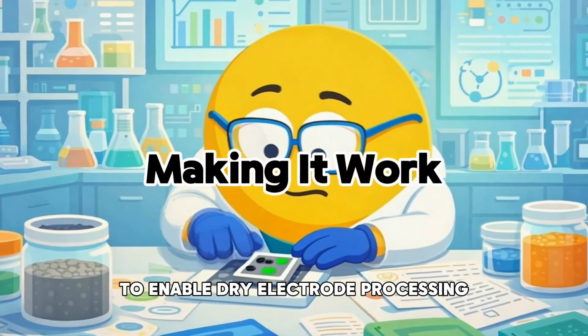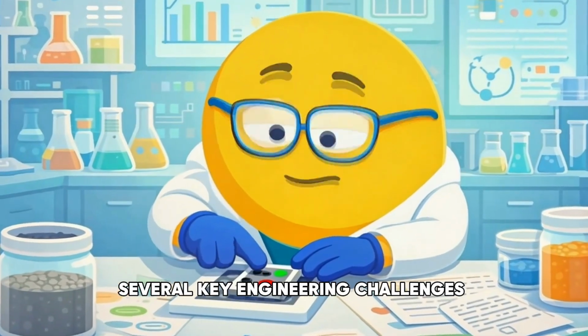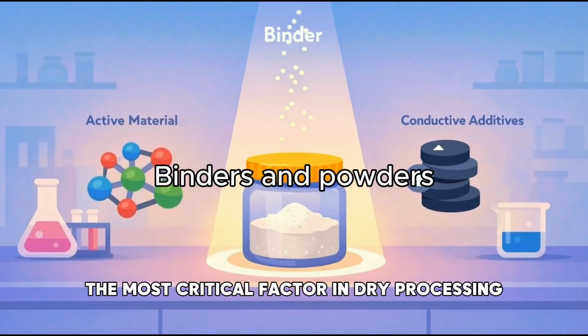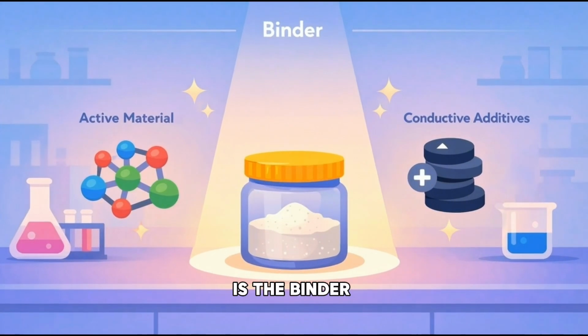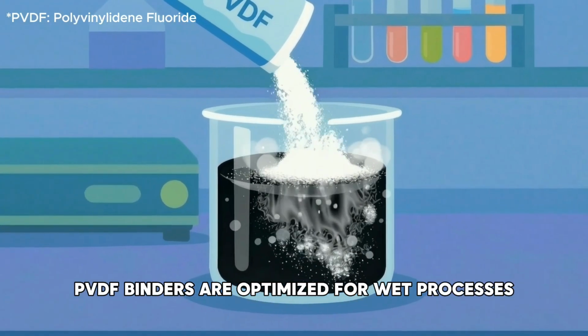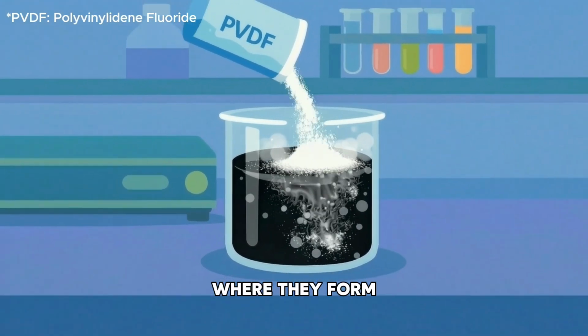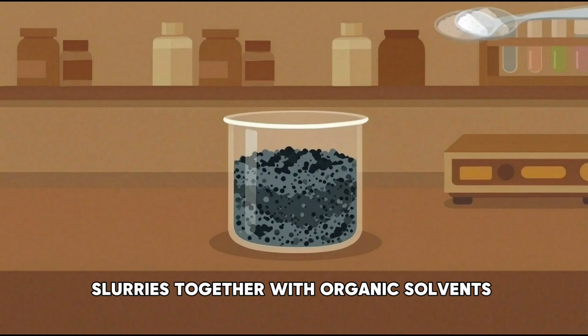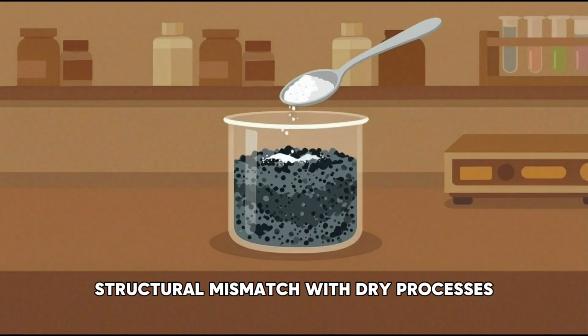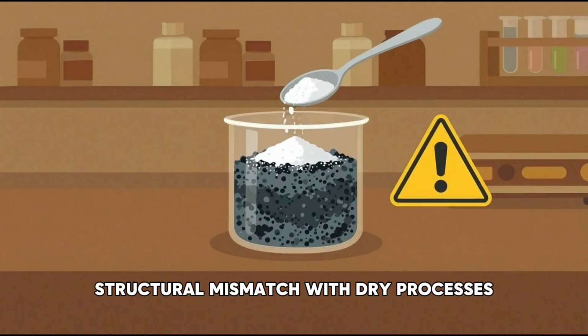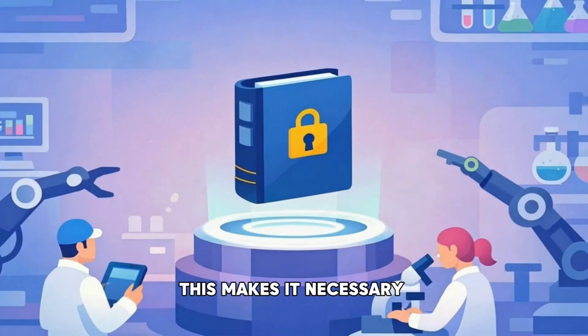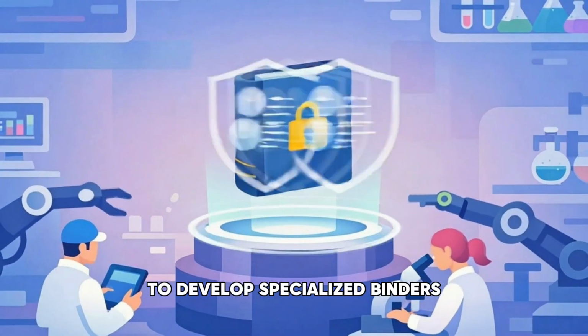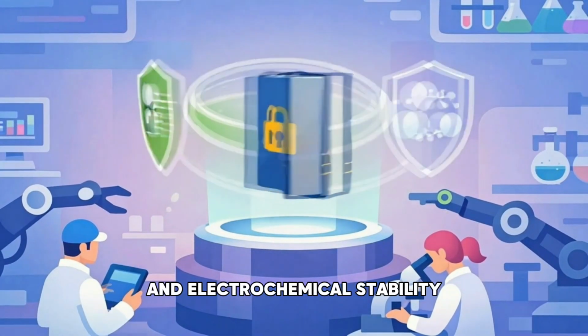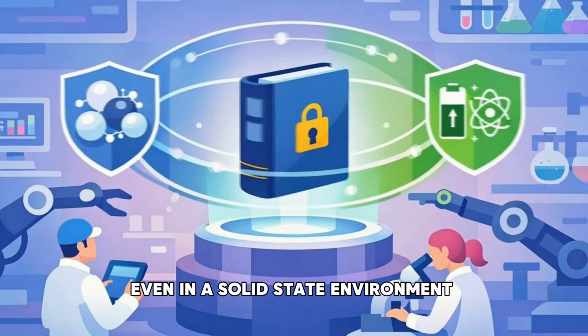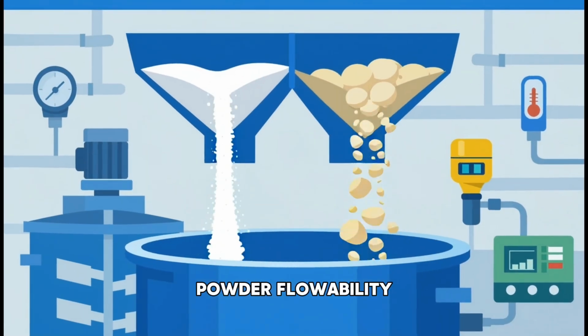To enable dry electrode processing, several key engineering challenges must be addressed. The most critical factor in dry processing is the binder. Traditional PVDF binders are optimized for wet processes, where they form slurries together with organic solvents. As a result, there's a fundamental structural mismatch with dry processes that don't use solvents at all. This makes it necessary to develop specialized binders that can provide strong adhesion and electrochemical stability even in a solid-state environment. Powder flowability is another crucial factor.